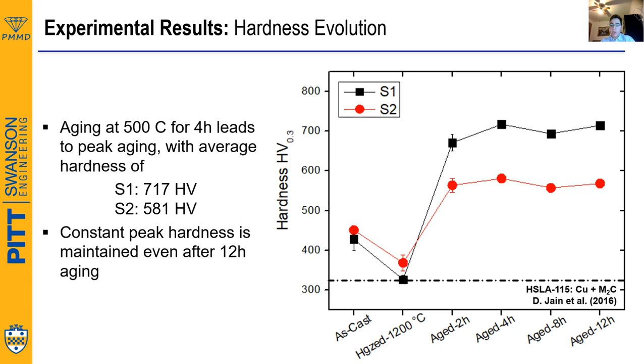Moreover, you see, based on the plateau shape of the data points, that the peak hardness remains relatively constant even after 12 hours of aging. Finally, here at the bottom of the figure, you can see that for the sake of comparison, the peak aging hardness of an HSLA 115 strengthened with copper and M2C carbide is plotted, to indicate as a reference how good our samples are doing when it comes to hardness, which testifies to the efficiency of L21 as a precipitate strengthening particle in the context of HSLAs.